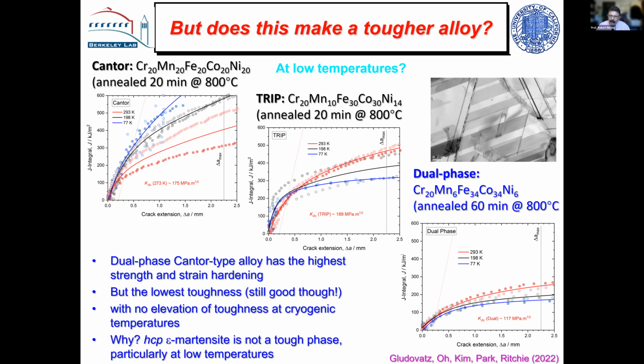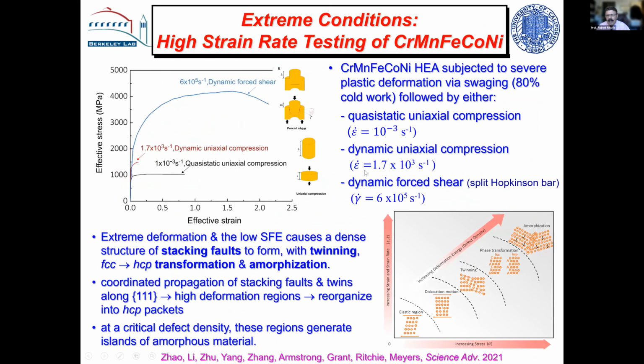So what happens if we go to extreme conditions? I'll quickly go through these. This is looking at this same Cantor alloy at very high strain rates. We started off with a uniaxial compression at 10 to the minus 3 per second. Then we went up to dynamic compression, where we're up about 6 orders of magnitude. And then we did the Hopkinson bar technique at about 7 orders of magnitude in strain rate. And so what we find here is we get very high strength. As you can imagine, we can get the strengths up as high as 4 gigapascals with this